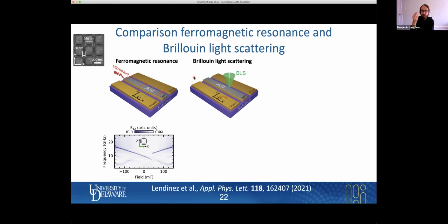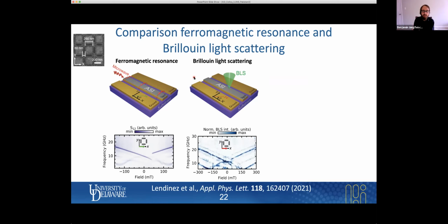And what we get is, again, frequency traces that we can record as a function of field. And then we get a color-coded image. Here, the dark color represents the BLS intensity, which is directly proportional to the number of magnons present in the system. And you can immediately see there are many more modes visible, and you see more pronounced this W shape I was referring to earlier. And this demonstrates we are sensitive to all magnetization directions, irrespective of their orientation with respect to the driving torque term. So we can see the eigenmodes of the system here very clearly using brillouin light scattering spectroscopy.